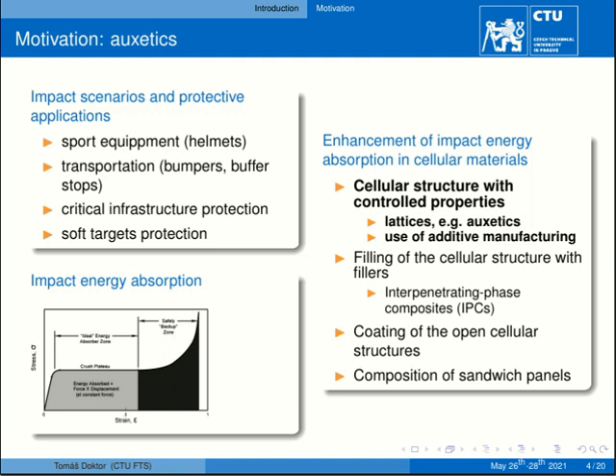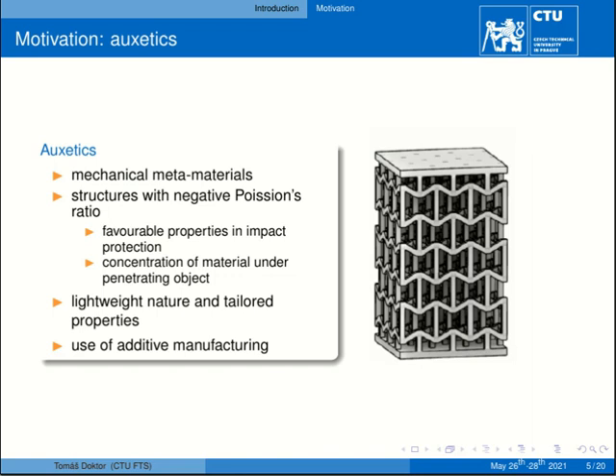Among cellular structures, auxetics are of high importance. Auxetics are mechanical metamaterials which exhibit negative Poisson's ratio. This means that such a structure shrinks under compression in opposite to standard materials with positive Poisson's ratio. This brings enhancement of impact energy absorption because the shrinking structure enables to concentrate amount of material under penetrating object and brings in this way a better penetration protection. Such auxetic lattices also preserve the lightweight nature and possibility to use tailored properties using additive manufacturing techniques.